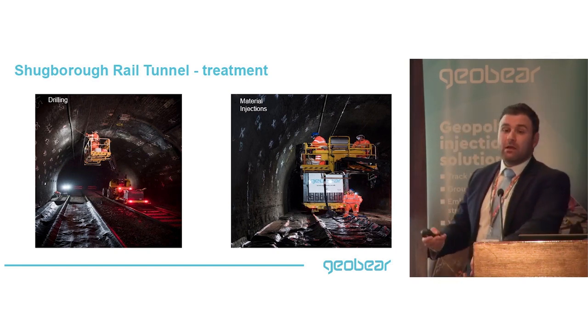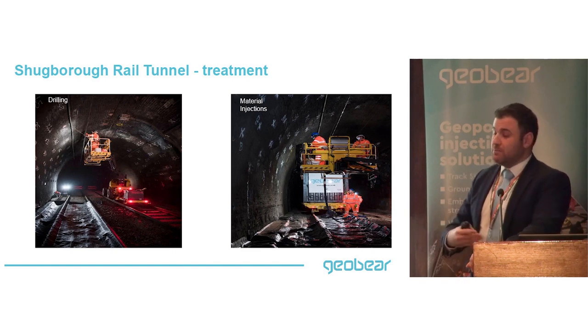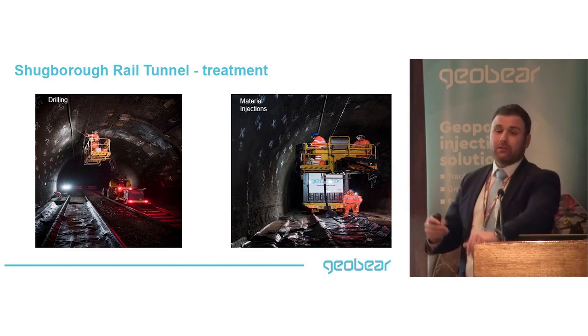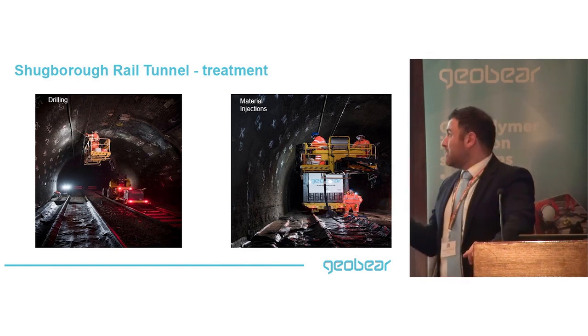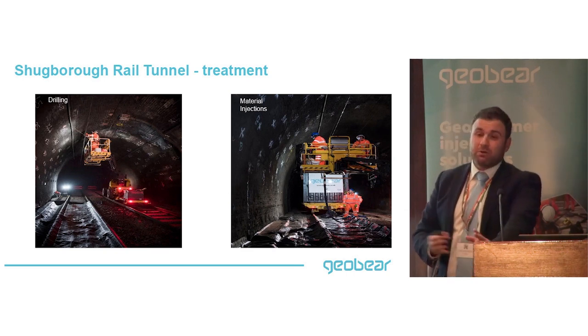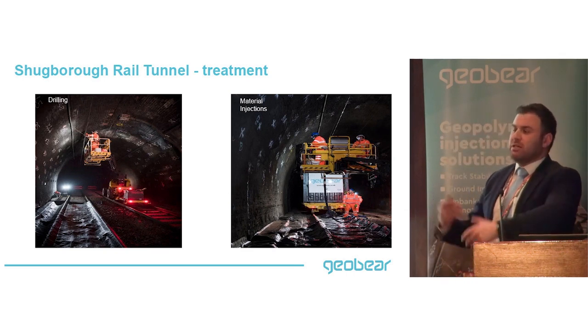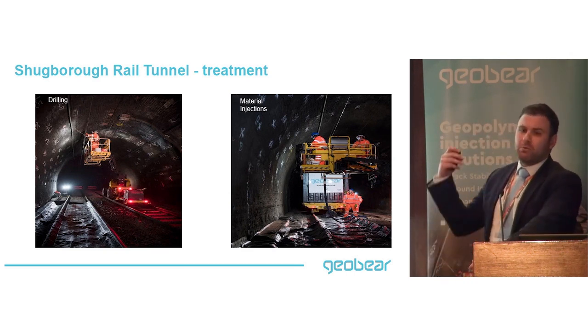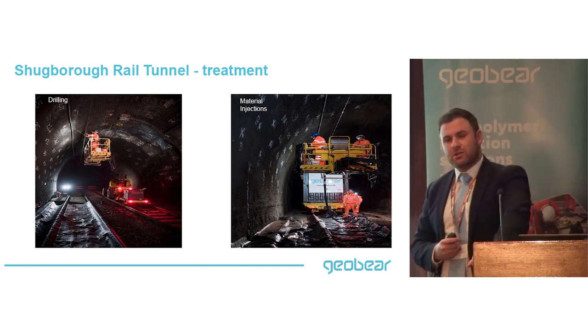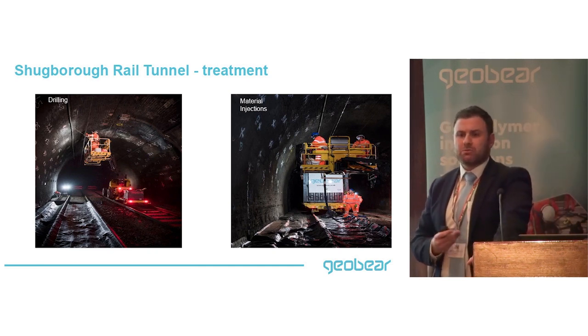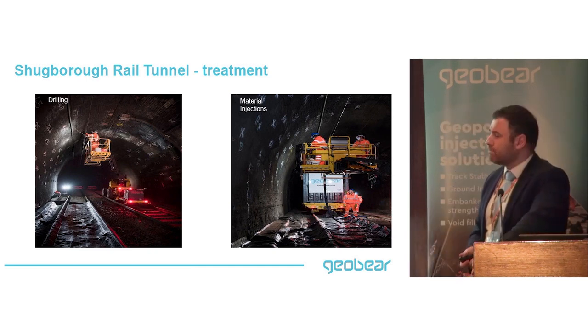And obviously you'd have an issue with flowability because you'd have to create bulkheads to contain the grout. With this approach, you get rid of all that problem, you don't need a bulkhead or any of that, and you get almost instantaneous solidification, reaching almost full strength within 6 to 8 hours.